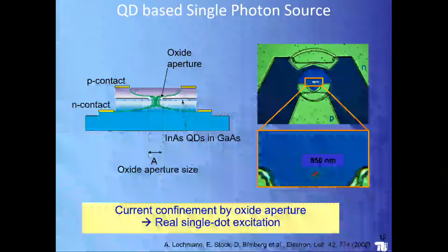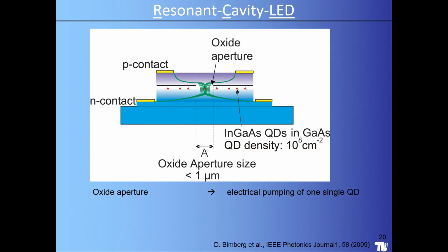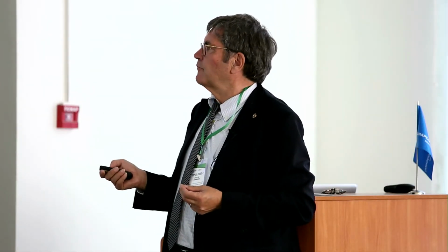Yeah? This is a very, very good trick, and that was the basis that we could really fabricate such a device. And this is already a high-frequency layout where we used a ground-signal-ground layout to enable high-frequency operation. And you see here the light coming out at 850 nanometers of one single photon.